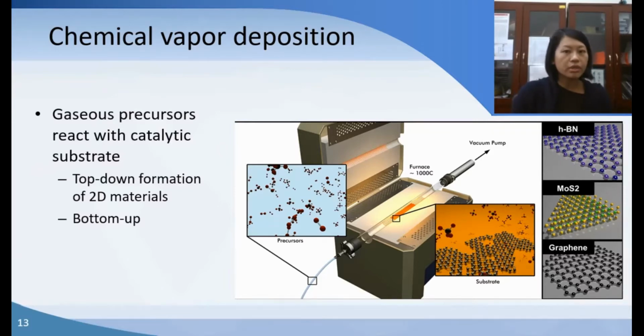To go on with that, I probably have to introduce how CVD works first. CVD usually requires a high temperature and some precursor that consists of the atom required to assemble into this hexagonal 2D material. So for example, for graphene, we will need methane, CH4, as a precursor to decompose into carbon radical, and then assemble this carbon radical into hexagonal carbon shape graphene.